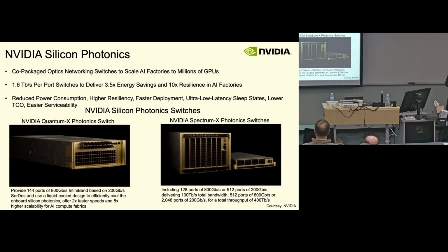The other big announcement from 2 weeks ago was NVIDIA talked about they're doing silicon photonics. This is the first time they really endorsed silicon photonics as what they need. So they've really been pushing NVLink, NVIDIA Link, for copper interconnects. And so they announced InfiniBand as well as Ethernet switches. But again, in their case, 200 gigabit per second, but using, again, silicon photonic modulators to get the data on and off those chips. And so that's generated a lot of excitement. Frankly, what they're proposing, what they're doing is pretty primitive, right? Compared to what I'll show and where most of the industry is, it's pretty primitive. It's a single modulator per fiber, right? And what I'll talk about is 8 to 32 wavelengths per fiber. But this is their first step, and they're growing.